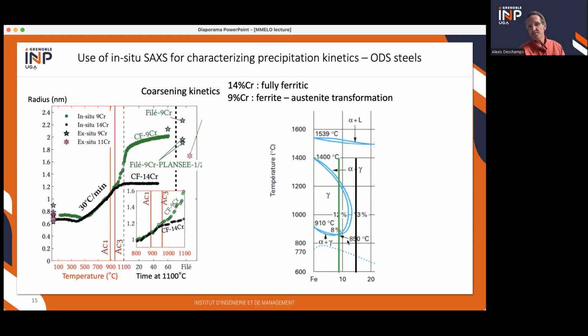And if you take another steel grade, which has exactly the same characteristics, except a lower chromium content at 9%, you are going through the gamma loop. So you have this phase transformation between ferrite and austenite during the process. And as soon as you get to the temperature where you have transformed into austenite, then the growth rate of these particles become much faster. And then it stabilizes somewhere around 2 nanometer instead of 1.2. And so this was a direct evidence from the in-situ kinetics that the phase transformation destabilizes the interface between the ODS nanoprecipitates and the matrix. So probably they become incoherent, and then their growth rate is impacted by this change of coherency.